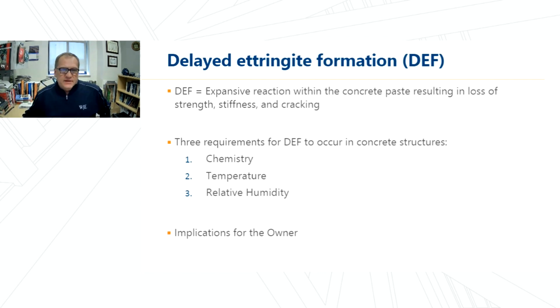So what does that mean? DEF is an expansive reaction within the paste that results in loss in strength and stiffness and eventually leads to cracking. Now, in order for this to occur, we need three things. We have three requirements for it to occur. One being the chemistry of the cement or the cementitious materials. We have to have the right chemistry in order for this reaction to occur.